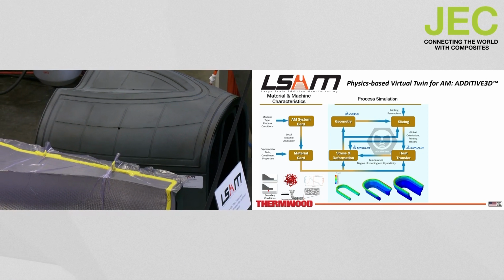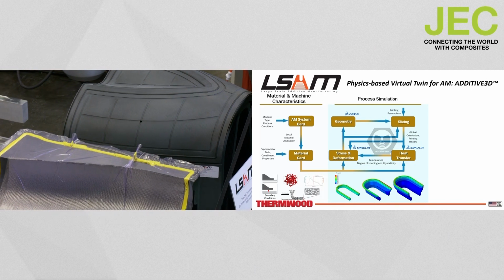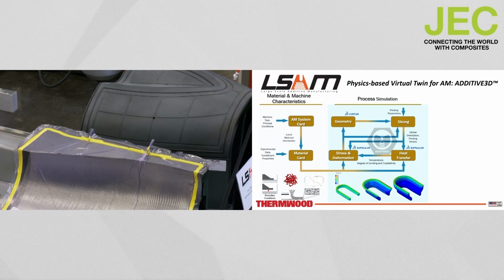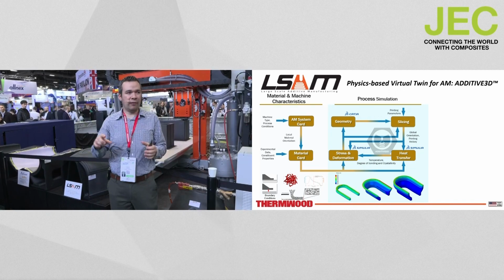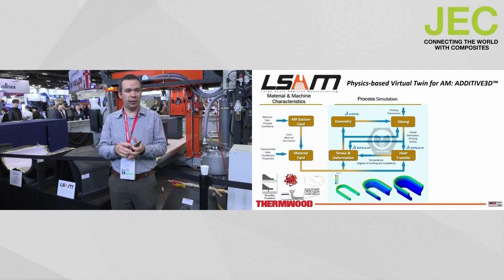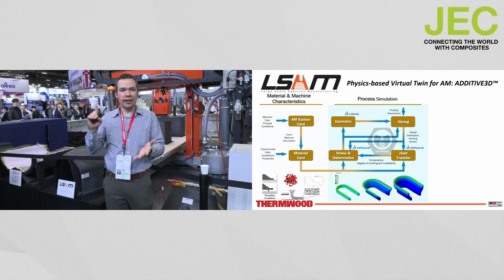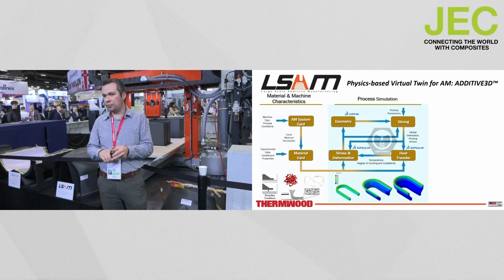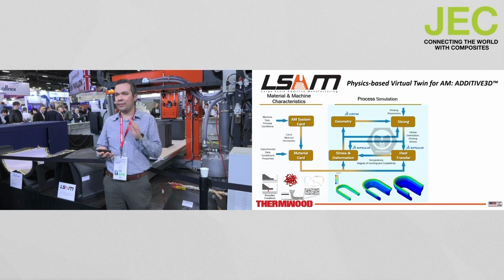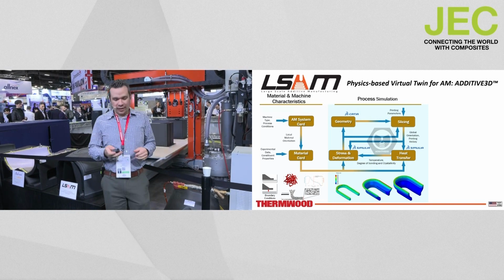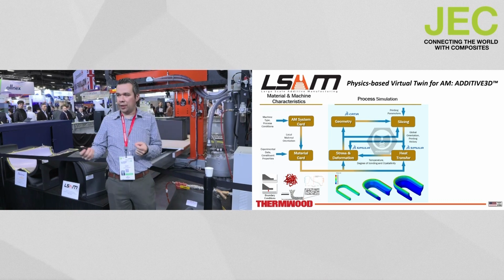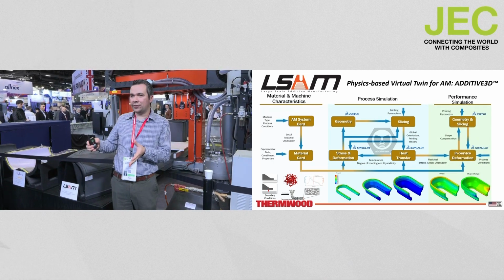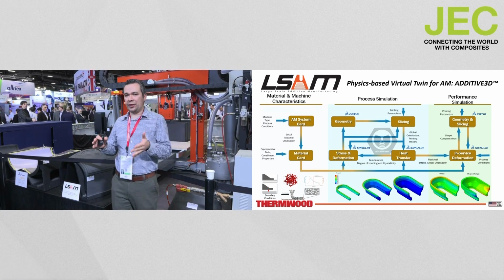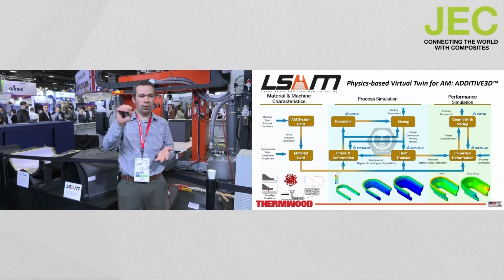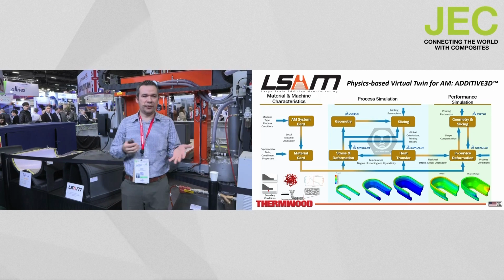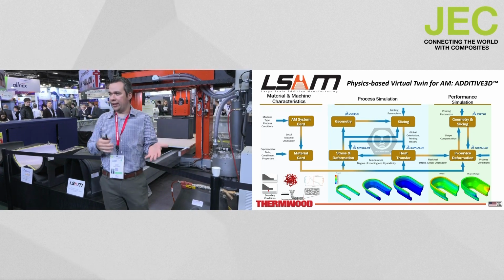The material and machine cards inform first the process simulation, where we take the machine code to drive the activation of elements in a finite element simulation while we solve that wide range of physics, including anisotropic heat transfer, anisotropic shrinkage, crystallization and melting in semicrystalline polymers and the corresponding shrinkage, the thermoviscoelastic behavior of the material, interlayer bonding, as well as the adhesion with the substrate. Then once we have gone through this simulation of the print process, we can look at the performance of the as-manufactured shape. In other words, considering all the effects of manufacturing, like residual stresses and local material orientation, we can pose questions like, how is the part going to perform when it goes in the autoclave? And we are able to predict and compensate for that.